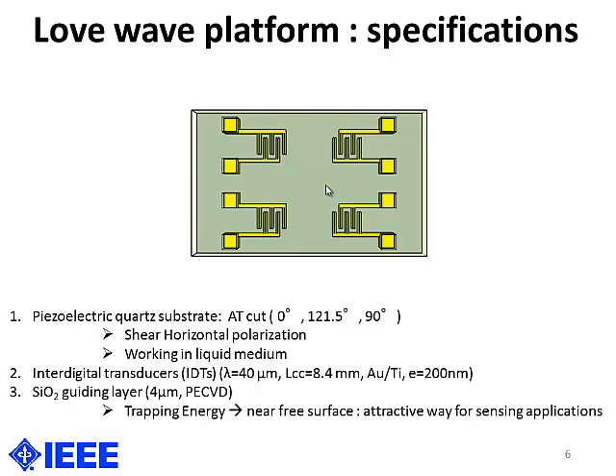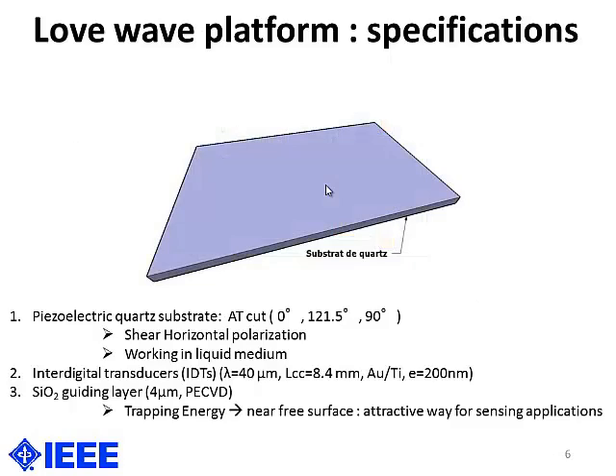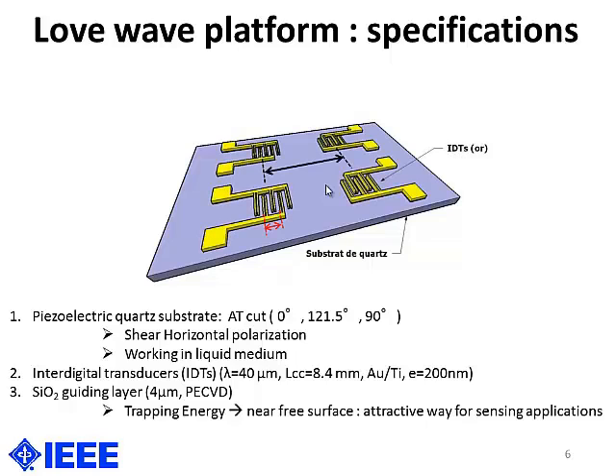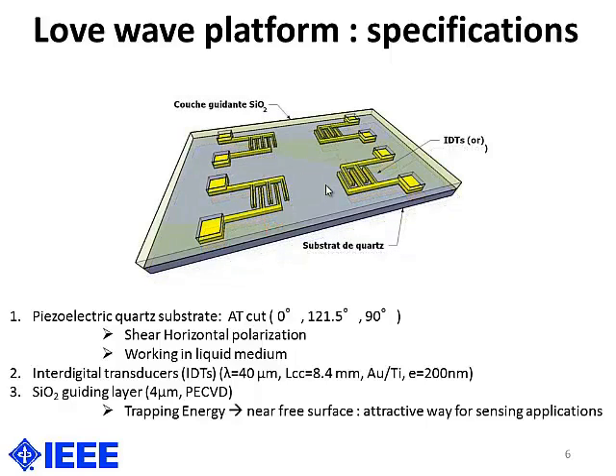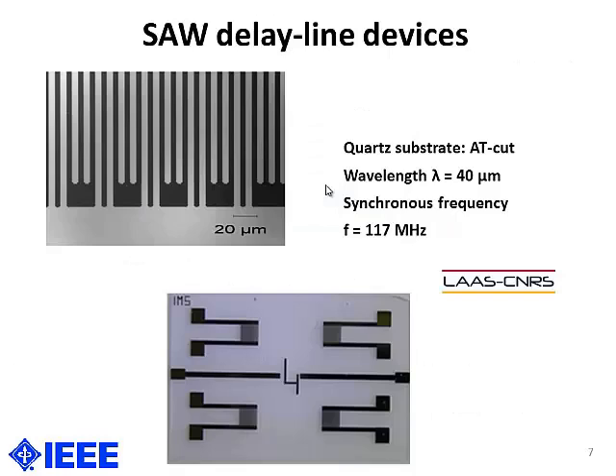Main parameters of our devices. It is based on a piezoelectric quartz substrate with a specific cut and with interdigitated electrodes. The global crystallographic orientation is such that we can generate pure horizontal waves, so that we can work with an adjacent liquid medium. Then a silicon dioxide layer acts as a guiding layer to trap the mechanical energy inside, and thus to emphasize the sensitivity towards surface effects.